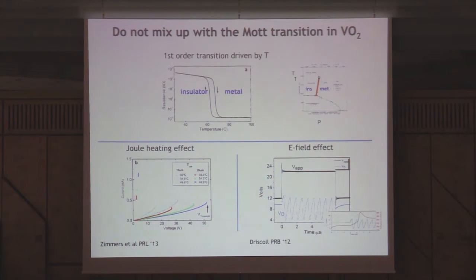So one warning is not to mix up what I'm talking about with the Mott transition in VO2. So VO2 is always also quoted as an example of a Mott transition. This is of a different flavor. There, your low temperature state is an insulator, and Ivan showed us that it's most likely that it's temperature which can trigger the transition from an insulator to the metal. There are groups which are not totally happy with that vision, and they propose that it's electronic driven.